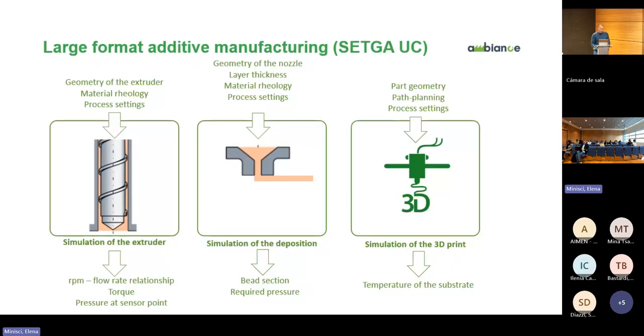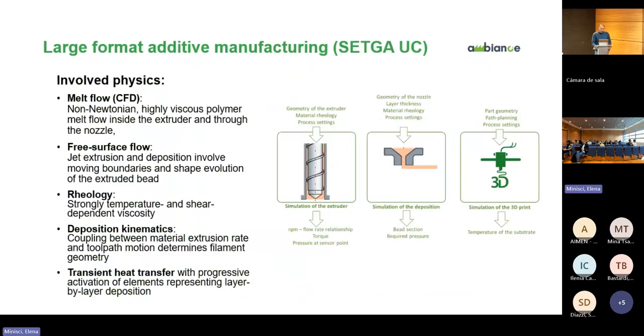The second model is dedicated to what happens in the very last portion of the extruder, that is the nozzle, and the interaction with the substrate. The substrate is where you deposit the melt polymer. And finally, another model is dedicated to the building of the component itself, the furniture or whatever. So what are the physics involved here? As I mentioned, we have a melt flow. So we are going to use CFD simulations, dealing with a non-Newtonian high viscosity polymer inside the extruder and through the nozzle.